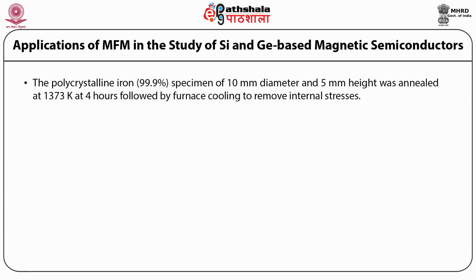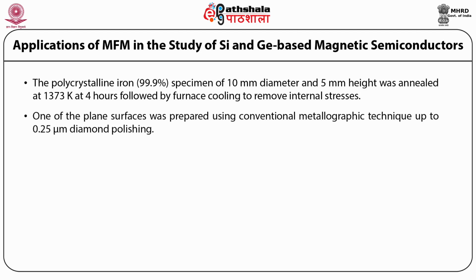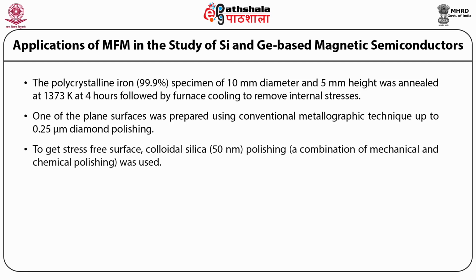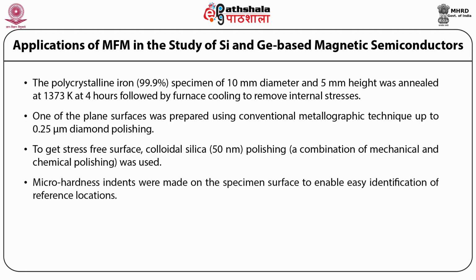The polycrystalline iron, 99.9% specimen of 10 mm diameter and 5 mm height, was annealed at 1373 Kelvin for 4 hours, followed by furnace cooling to remove internal stresses. One of the plane surfaces was prepared using conventional metallographic technique up to 0.25 micrometer diamond polishing. To get a stress-free surface, colloidal silica polishing was used. Micro hardness indents were made on the specimen surface to enable easy identification of the reference location.